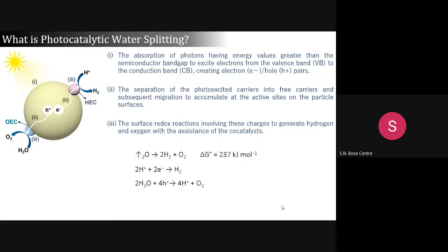So basically it involves three fundamental processes: light absorption and exciton generation, exciton splitting and moving to the surface, and the surface reaction. As you can see, for water splitting the delta G is almost 237 kilojoule per mole, so it's a thermodynamically uphill reaction. So you need to be very careful to get good efficiency, because once you get the sunlight, there will be several processes which decrease the efficiency of this hydrogen production. For instance, the recombination of the hole and electron, and the trapping of the hole and electron in different places of the semiconductor.